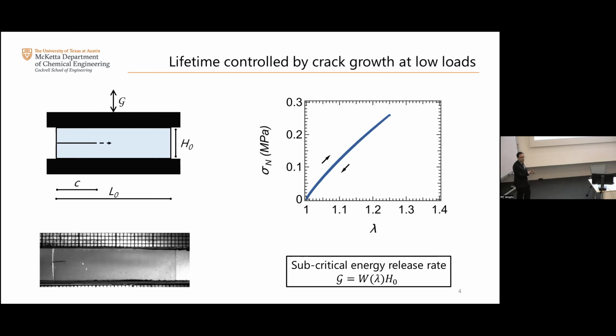And because the system is very elastic, it's an elastomer after all, you have basically superimposing loading and unloading curves, meaning that all the work that you do to the system and all the energy that is stored, you can recover it. And that's the beauty of an elastomer, right? But when you actually have a pre-crack or a defect in your system, we all know that eventually it's going to break. So now the experiment is slightly different.